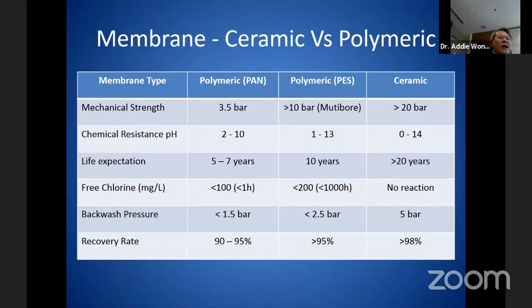So how is the comparison of ceramic and polymeric? Here you can see polymeric membrane, for example PAN, can take a pressure of only 3.5 bar. The PES multi-bore, which I just showed, where one fiber has 7 bores, can take slightly more than 10 bar. The ceramic membrane can take above 20 bar. For chemical resistance, you can see they are getting better and better, and ceramic is very resistant. So life expectancy is higher for ceramic.